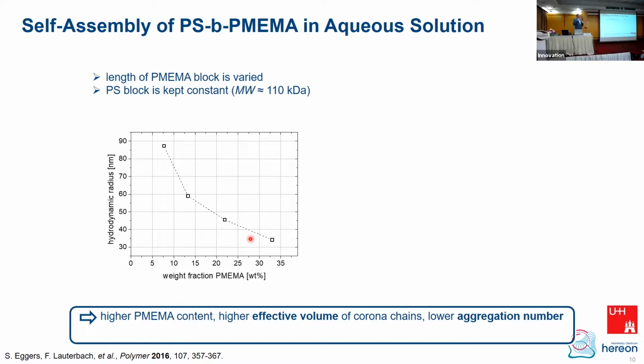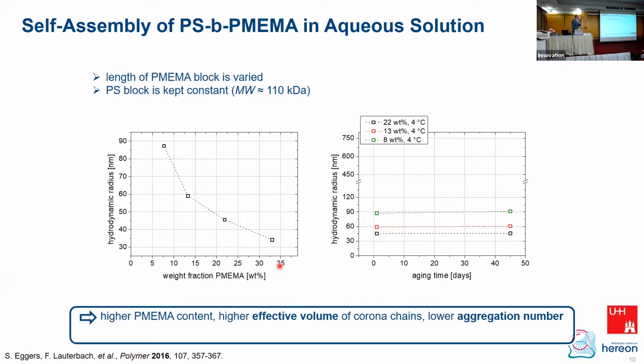And the interpretation is that when you have this block polymer dissolved in THF, it's completely dissolved, and then you put it into the water. Now you get the aggregation. Since for the polymers having the larger polymer block, they require more space. These polymer blocks are nicely dissolved in water, so they are very expanded. Due to that, there is not so much space in the core. So you have to have a stronger curvature of the core in order to generate more space in the corona for the individual polymer block. And that means the aggregation number is getting less if you have the larger water-soluble block. And in total, it means that the whole thing becomes smaller, because it's less chains which are forming one aggregate, one micelle. And also interesting was to observe that there's an aging effect.